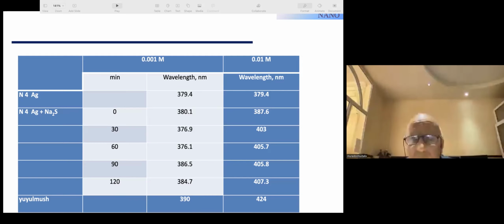And here we showed the maximum of plasmon oscillation depending on the modification process for low concentration of sodium sulfide. In low concentration of sodium sulfide, we can show that it changes with the time of modification.